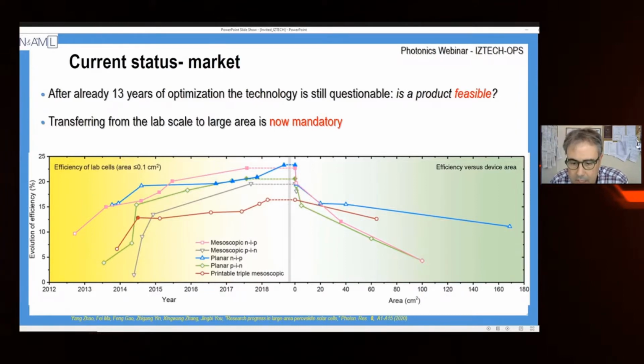But on the other hand, we need to find a way to transfer this technology from the lab to the enterprise. As you can see here on the left, we have some of the efficiencies obtained in the lab in a small area. You can see that they are pretty high. But when we transfer this technology from small size to larger area, you can see that now we have a decrease in this efficiency. As soon as you increase the size of the device, of the module, of course, you can get even lower performance.